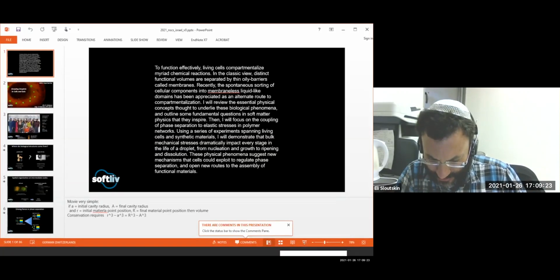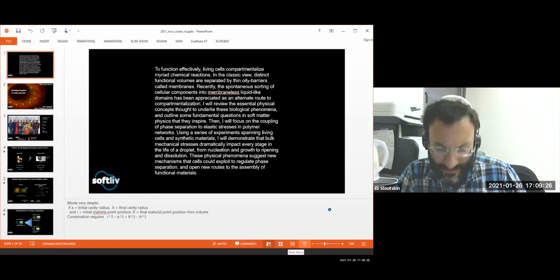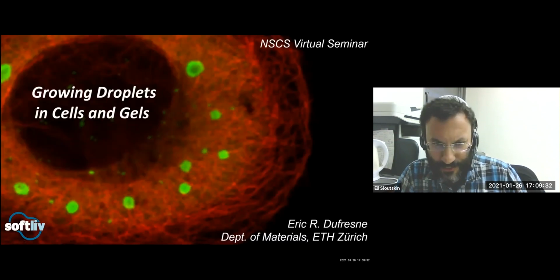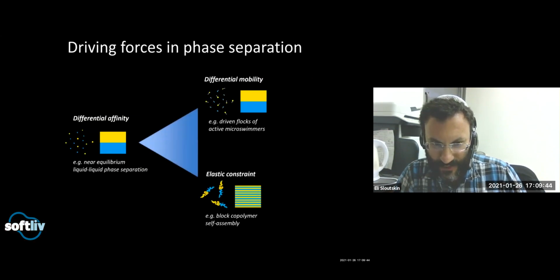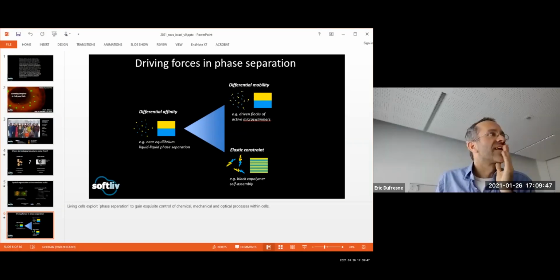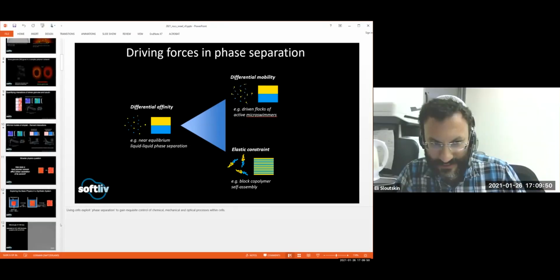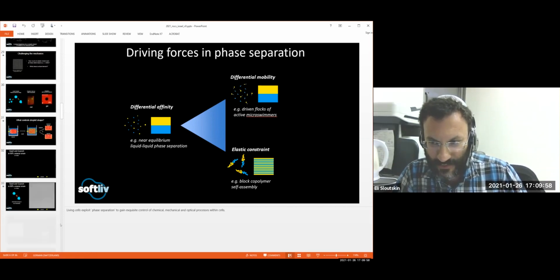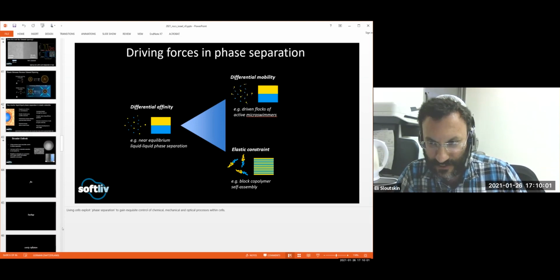Eric? Yes. So two questions. First, the technical one. The last plot which you have shown was the temperature where the droplets form as a function of the modulus. And there was a mismatch between the theory and the experiment, which you suggested may be related to remnants of nucleation problems. If it is so, then that's a simple experiment to do. You can just go the other way around, just heat the droplets and measure, which you did, and plot on the same plot the temperatures of their dissolving, right?